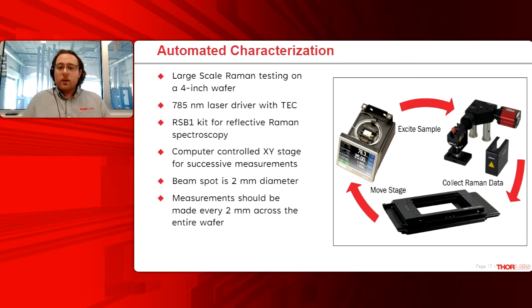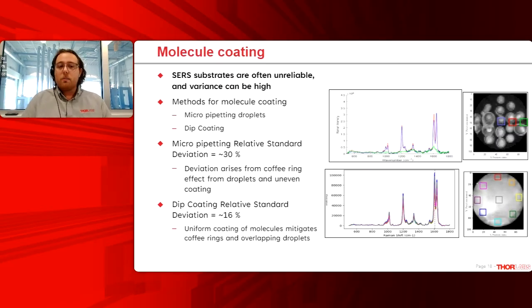So how do we measure this uniformity? What metrics do we use? Well, this is actually highly dependent on how you coat the molecules onto your surface. In this case, I want to remind people that a common issue with SERS substrates is that they can have a high variance or a high relative standard deviation. Now, some common methods of applying your molecules to a SERS substrate could be micropipetting. In this case, you take a fixed volume of your molecules and you place a drop on the surface.